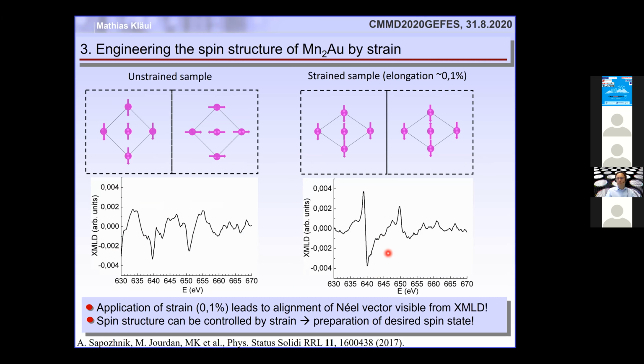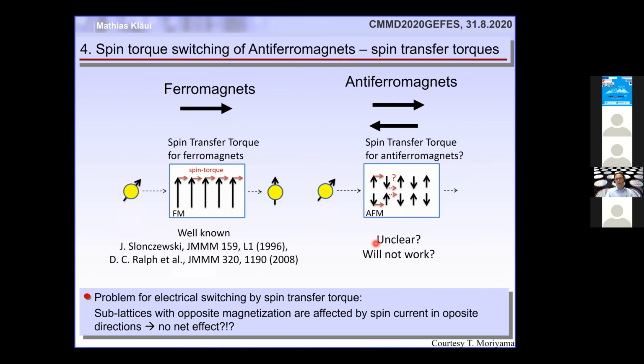However, again, if you talk to people from industry, they're not interested in putting a medieval torture device into their sample, so they would like an all electrical switching. And electrical switching in ferromagnets is well known. These are spin transfer torque effects, where you inject a spin polarized current, and that spin polarized current actually exerts a torque on the magnetization by transfer of spin angular momentum, and therefore rotates the magnetization. However, in antiferromagnets, this might not work, because you see here there is a spin polarized current coming in, and it means one sublattice will actually rotate this way and the next sublattice will rotate that way. So they will rotate in different directions, and due to the strong antiparallel coupling, there might be no net effect.